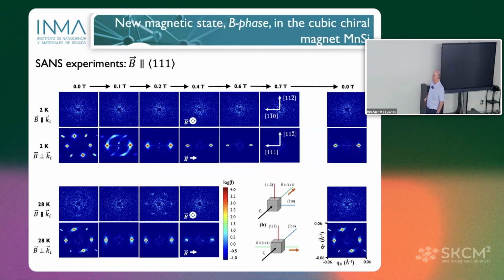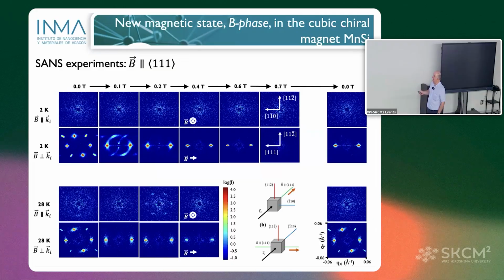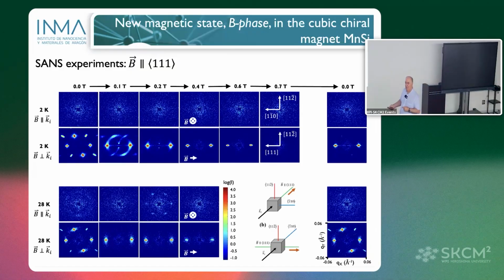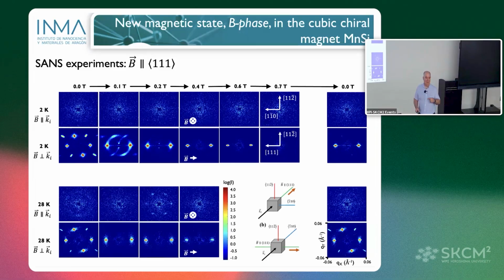And here are the experiments at 2 Kelvin and 28 Kelvin, with magnetic field parallel to the 111 direction. This is the crystalline direction, and then parallel to the incoming neutron beam, that means skyrmion configuration. We don't see at low temperature any signature of skyrmions as we increase the magnetic field. However, if we put the 111 direction perpendicular to the incoming neutron beam, we observe these 2 satellites that are related with the main diagonal 111, and we observe other satellites that are related with other main diagonals, 1, 1, minus 1, there are 4.